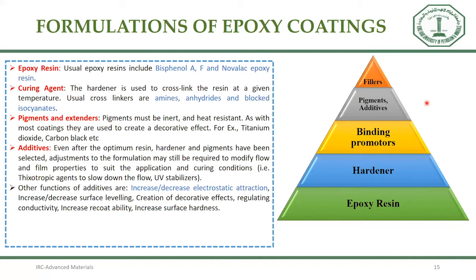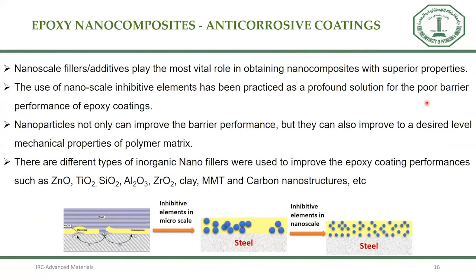Nowadays, instead of taking innovative pigments on the micron scale, we try to use nanoscale materials, because adding nanomaterials into the polymeric matrix can increase the barrier performance. Not only barrier performance, it can also alter other properties like thermal and electrical properties. The importance of utilizing these nanomaterials in the epoxy matrix is that they can improve the polymer and matrix interaction. And when you consider nanomaterials, we know the important feature, that is a large surface area to volume ratio. By using this, we can easily improve the properties of the resultant polymer, here epoxy.